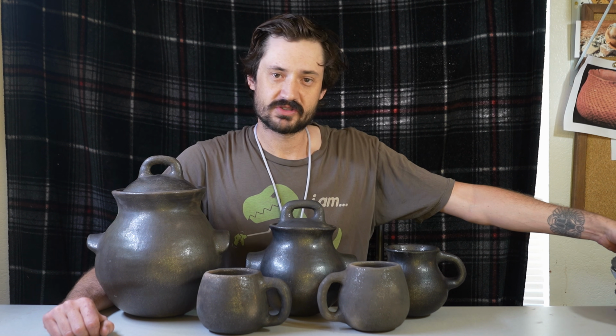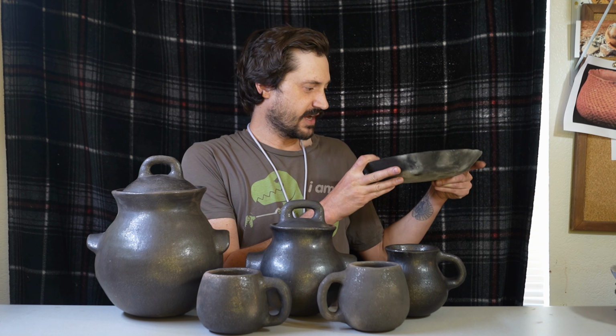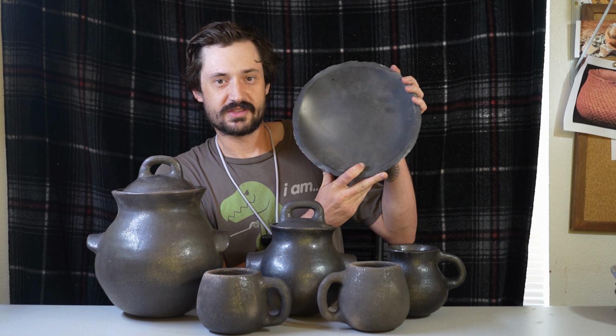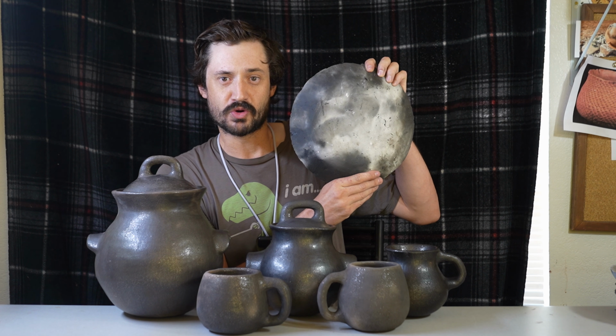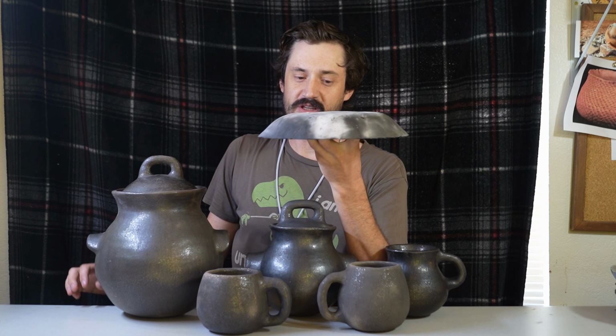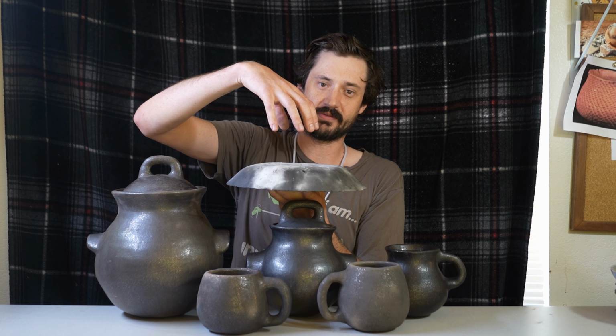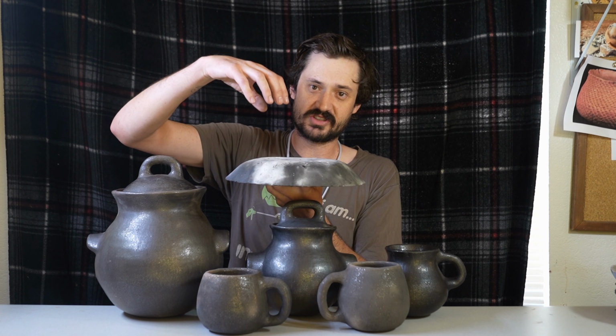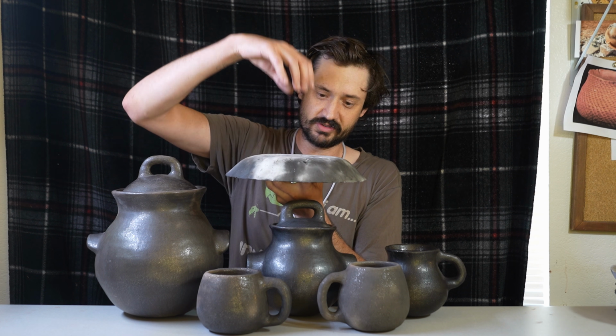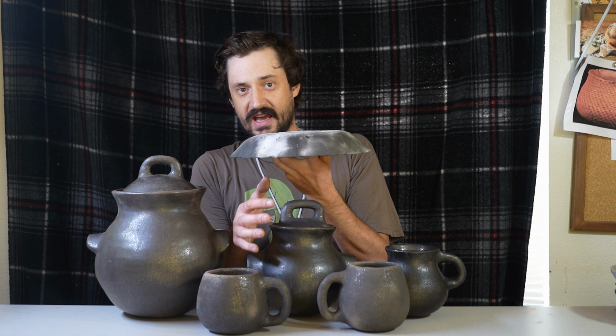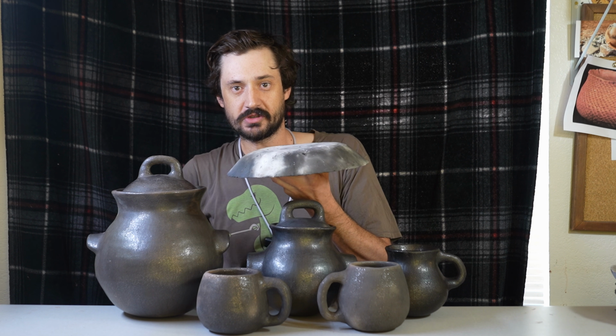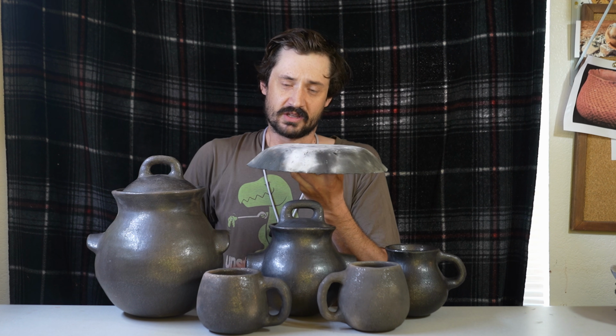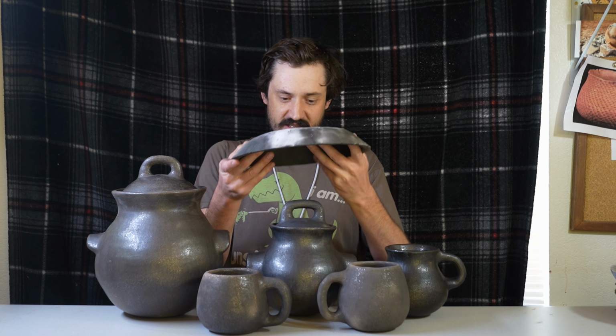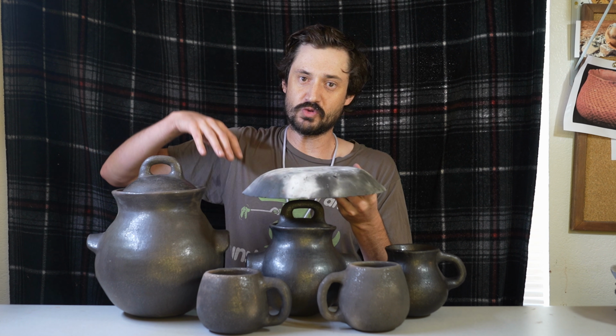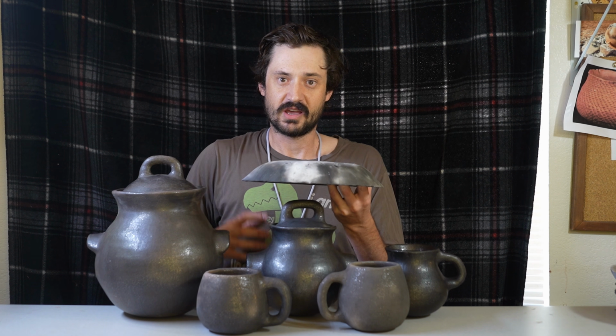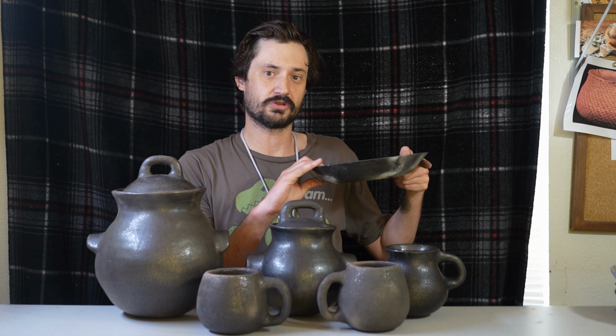Next, I wanted to talk about cover sherds, because I believe they were key to this successful carbon blackening firing. You'll notice on the inside a thick carbon blackening, while it's considerably more patchy on the outside. What I believe happened is I added the organic material before smothering. I smothered, and then that carbon dense smoke was pushed through all of the coals past the cover sherds, and it sat in that little controlled microclimate under the kiln furniture exactly as is supposed to happen. That really highlights the importance of cover sherds in creating a little controlled environment that lets fumes in but keeps large debris from falling in and keeping that carbon from attaching to the pots that you're trying to smother.